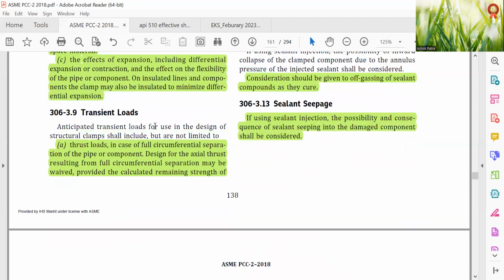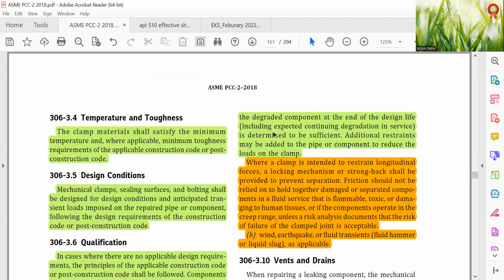Transient loads, thrust loads in case of full circumferential separation of the pipe or component: design for the axial thrust resulting from full circumferential separation may be waived, provided the calculated remaining strength of the degraded component at the end of design life, including expected continuing degradation in service, is determined to be sufficient. Additional restraints may be added to the pipe or component to reduce the loads on the clamp.